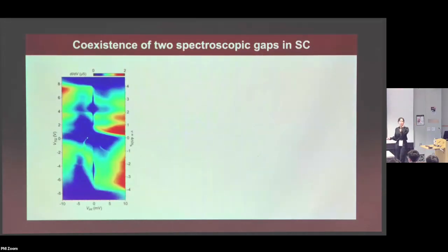But there's still another concern remaining for me: what if, within one tunneling spectrum, there might still be different coexisting, complex, competing gapped phases in that superconducting phase? So that is still remaining, and we still want to investigate that part. And it turns out that that was actually the case. So here's the tunneling conductance now in some intermediate energy range. Wherever we were looking at a very small energy scale, like 0.3 milli-electron volt, here in these pink regions.